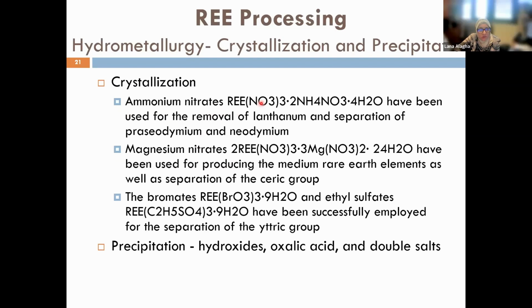ammonium nitrate double salts. Usually they are used for the removal of lanthanum, praseodymium and neodymium. Magnesium nitrate double salts are also used usually for the medium rare earth elements, and for the heavier rare earth elements or yttric group, bromates and ethyl sulfates are also used. Precipitation techniques using either hydroxides or oxalic acid or double salts are also utilized to precipitate rare earth compounds.